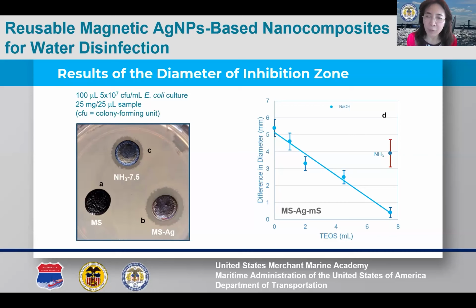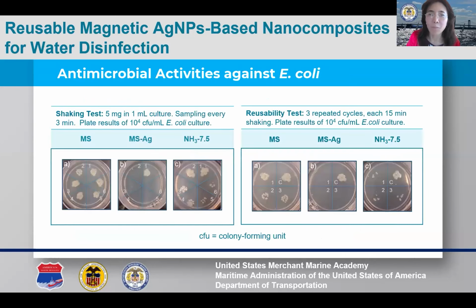When 7.5 milliliters of TEOS was used, the shell thickness increased to about 80 nanometers, and the inhibition zone became hardly visible. This demonstrated the tunability of the mesoporous shells for controlled silver release. All of this reaffirms the critical role of silver in the biocidal activity of the nanocomposites.